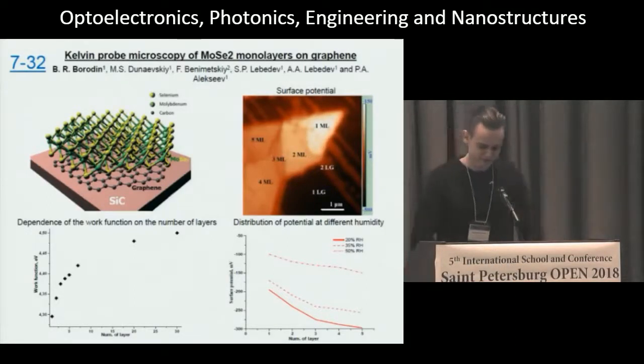Hello, ladies and gentlemen. The theme of my work is Kelvin probe microscopy of molybdenum diselenide on graphene. This system has emerged as attractive for novel nanoscale electronic devices. The dependence of the work function and surface potential on the number of layers was shown in this work. This data can be important for detecting the number of layers of molybdenum diselenide.